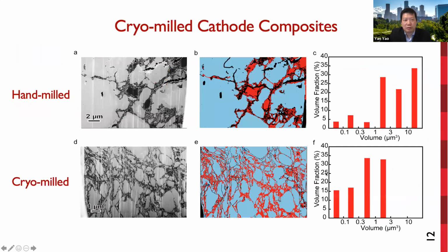To further improve materials utilization, we look into optimizing the microstructure of the electrode. In contrast to NMC particles, which have uniform shape and size, organics typically have a wide distribution of the shape and the size, making it very difficult to engineer the microstructure. So we discovered a cryo-milling process can greatly reduce the PTO domain size.